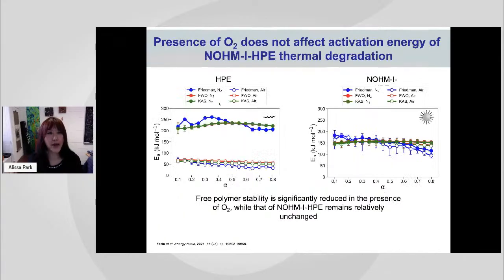So we went back and measured the activation energy of thermal degradation of these materials. Again, left is an untethered polymer, right-hand side is a NOHMs-based material. There were very unique behaviors. As we expected, for the untethered polymer on the left-hand side, high activation energy was observed under nitrogen condition, but as soon as we introduce oxygen, the activation energy was significantly reduced, so that the polymer decomposed very quickly. But if you look at the NOHMs, regardless of the presence or absence of oxygen, the activation energy of the thermal degradation was very similar. We now hypothesize the reason for this is both thermal and also kinetics. The mass transfer of oxygen through NOHMs was much slower compared to CO2. Also, the end cap of nitrogen groups was stabilized by tethering polymers onto nanoparticles.